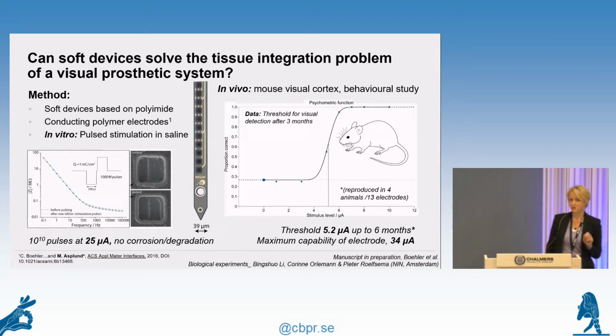And this way you can investigate which current threshold you need to reach to generate a percept that the mouse can actually then see with this artificial interface. And where we're at right now is that we can see that around 5 microamps is what we need to push out of an electrode to generate one spot of light. And this is well within what these small electrodes can do, which means we have every reason actually to be optimistic that we have solved some of these fundamental problems with long-term stability of these kind of interfaces.